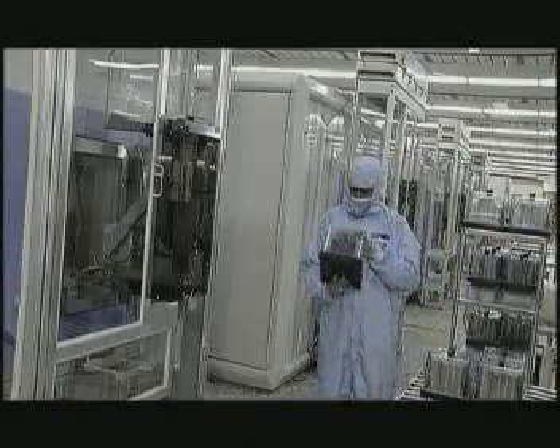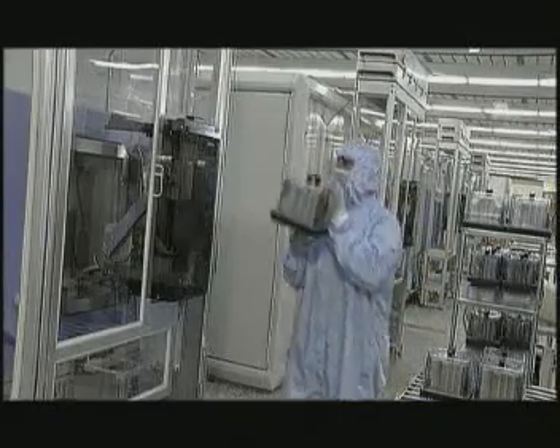The templates themselves are made by other specialists. It goes without saying that we also cooperate very closely with these suppliers and equipment manufacturers. In these so-called implanters, specific atoms can be shot into the unprotected areas of the silicon to give them a positive or negative conductivity. This is done incredibly accurately — for example, one atom in a hundred thousand silicon atoms.